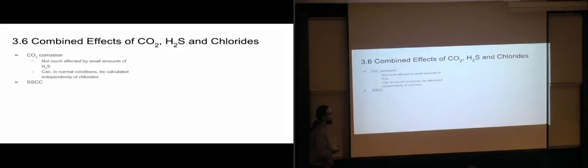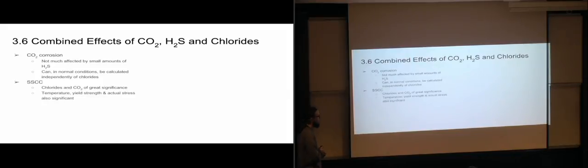Then you have the cracking, SSCC, where chlorides and CO2 are of great significance, so they're going to greatly impact the risk of having this cracking happen. And the temperature, yield strength, and the actual stress in the situation are also very significant for the sulfide cracking.